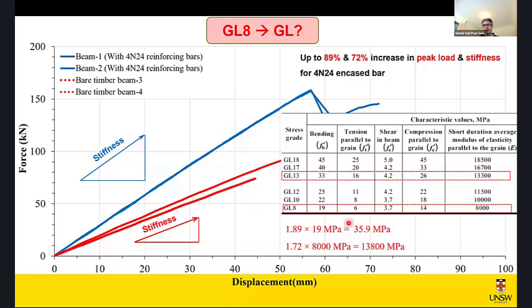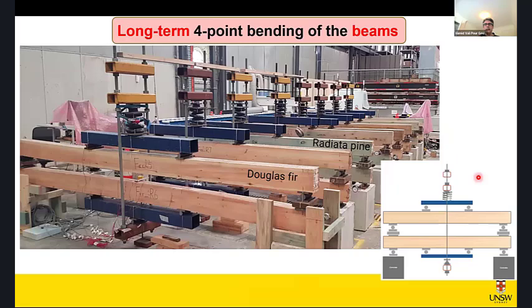In fact, this bending strength is closer to, I would say, GL15. Some of the glulam beams of GL15 I have seen on the market have a bending strength of 36 MPa, which is very close to that one. And the elastic modulus is even slightly higher than GL13, but let's say it's GL13 for now. So you see the substantial improvement in the strength as well as stiffness.